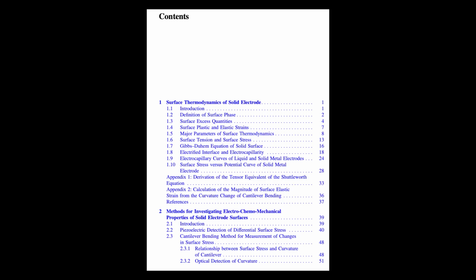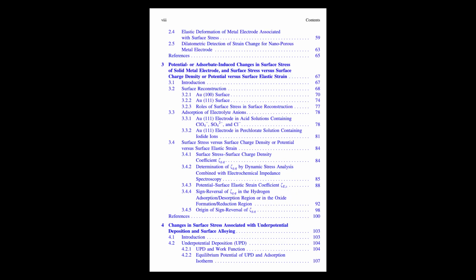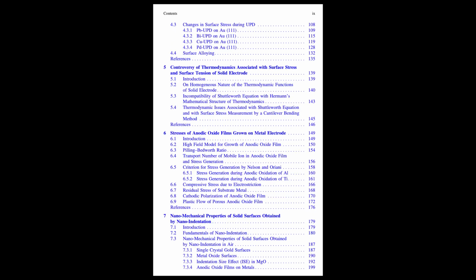Okay. And nano-indentation isn't just for simple materials. We can use it on pristine single crystal gold, carefully prepared without any oxide, to get the intrinsic properties of the metal surface. We can use it on those metal oxides we talked about, like TiO2 and magnetite, to get actual numbers for their nanoscale hardness and elastic modulus. For instance, doping TiO2 with niobium can make the hardness pretty constant over a range of indentation depths. So you get direct numbers for how resistant these oxide surfaces are to being deformed.